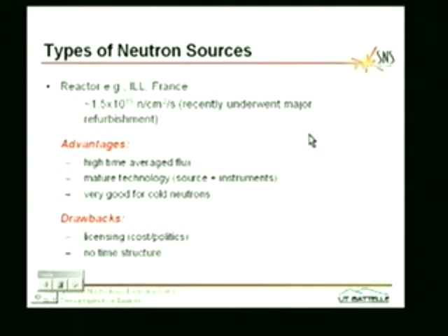So just keep that in mind, and I'll get back to it in a second. So the benchmark for a research reactor is the high flux reactor in Grenoble. It's got a peak thermal neutron flux in the core of a little over 10 to the 15 neutrons per square centimeter per second. It was just recently refurbished.